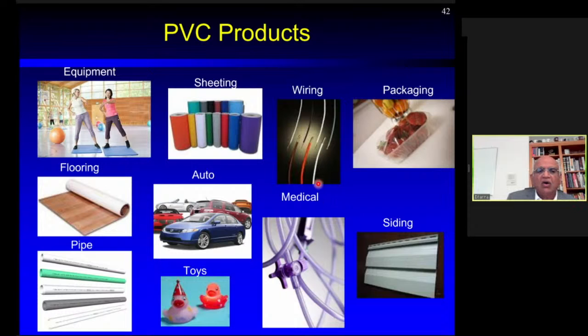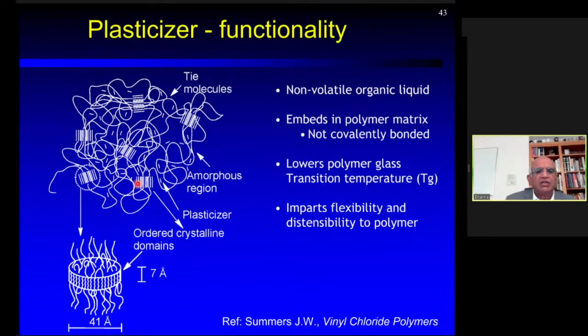Let us see how this plasticizer's function is shown here. The PVC polymer structure is shown here. It has two regions. One is the ordered crystalline domain, as well as the amorphous chains that are shown here. When this polymer is mixed with an organic liquid and compounded well, the small organic molecules get embedded in the amorphous regions without any covalent bonding. They lower the glass transition temperature of the polymer, thereby imparting flexibility to the polymer. That is how the plasticizers function. So with that understanding,